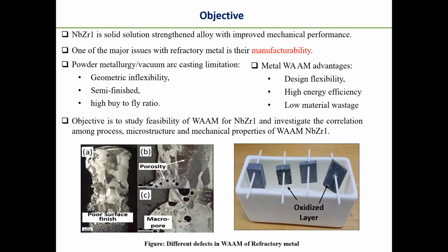With respect to them, metal AM has lots of advantages like design flexibility, higher energy efficiency, and low material wastage. But the major problem with AM is it has different kinds of defects, like poor surface finish, lots of porosity, and high temperature oxidation with respect to the refractory metal. So our studies focus on the feasibility of AM of niobium zirconium refractory alloy and to investigate the correlation among the process, microstructure, and property.